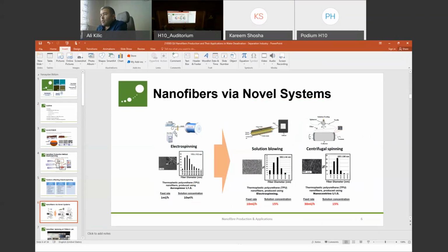As I mentioned, we were using electrostatic forces, but we said, what if we use compressed air? Using compressed air, we can again form fibers, and larger compression forces are applied to this polymer jet. After doing some preliminary studies, we saw that we were able to increase the feed rate to very high values, which is 10 times that of electrospinning. On the other side, since we have higher mechanical forces, the solution concentration can be larger. Another study we focused on was the use of centrifugal forces.